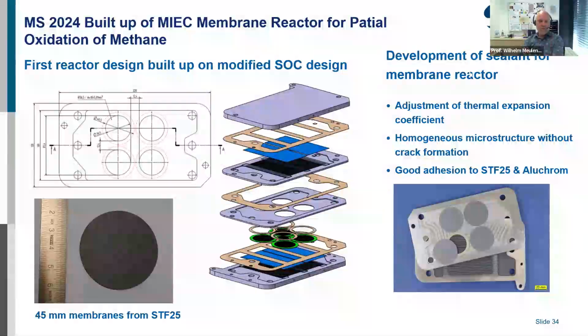And then the next step, what we plan to do this year, is we want to bring one reactor in operation and to demonstrate that the partial oxidation of methane with such a mixed conducting membrane is possible. And then the first question was, which material we want to select for this reaction. So we have a very high driving force in this reactor, but we need a very stable material in very harsh conditions, including CO2 and maybe some SOx in the gases. And then we decided to go for an STF25, so a strontium titanate-based material, which has under these conditions also reasonable performance, which can be compared with LSCF.